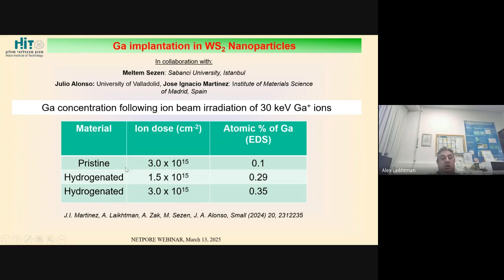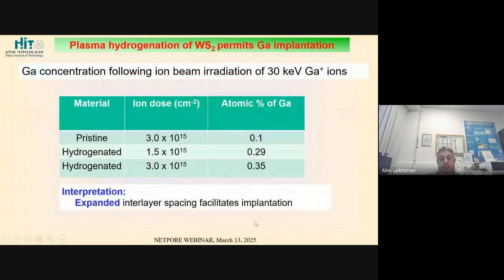We tried the same process with previously plasma-hydrogenated nanotubes, and to our surprise, because we did not expect this, the atomic concentration rose 3 to 4 times, which is quite sufficient for doping. We published this result, which I will present in a moment, less than 1 year ago in Small. Our interpretation was related to expanded interlayer spacing because of hydrogen plasma treatment, which we observed when we considered these nanotubes as hydrogen storage media, which I talked about several minutes ago.